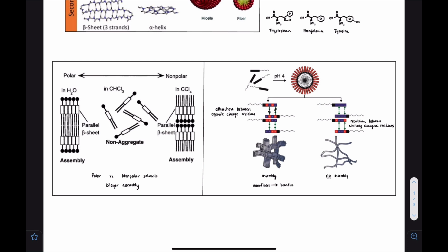With strategic design, peptide sequences can be placed in a manner where they can attract or repel other peptide amphiphiles. These self-assembled nanofibers bundle due to interactions with neighboring nanofibers. Here, the design achieved a pH-responsive system via charged residues arranged in a complementary attractive fashion, resulting in the bundling of nanofibers, and those in a complementary repulsive fashion, which results in dispersed fibers.